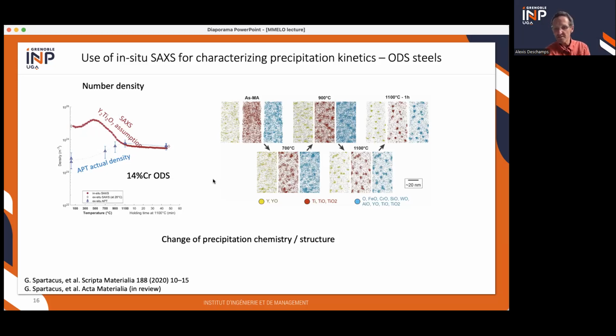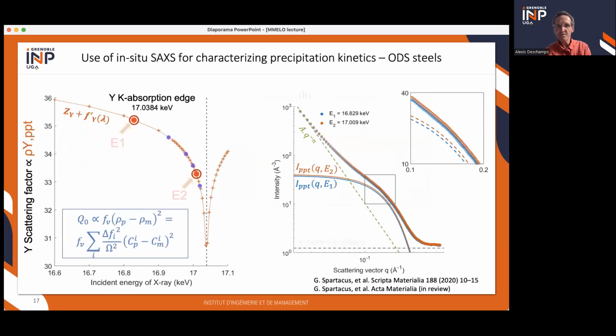So to try to understand this in more detail, we use a particular technique of X-rays. One possibility offered by synchrotrons is to change continuously the X-ray energy. And when you get close to an absorption edge of one element, for instance here yttrium at 17 keV, then the scattering factor of this element becomes lower. And if you change the scattering factor of this element, it's like changing its number of electrons. And since the intensity you measure is proportional to the contrast of scattering factors, the contrast of electronic density between the precipitates and matrix.